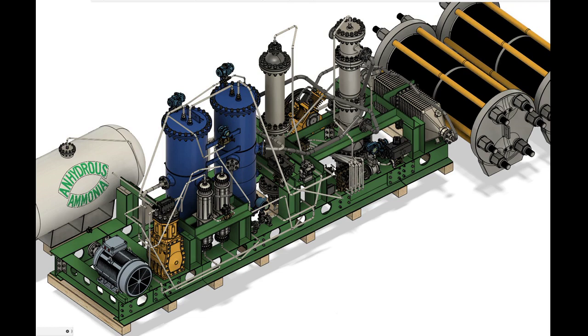In the paper, Hydrogen Attack on Metals at High Temperatures and Pressures, Corrosion and Material Protect, by J. Schutten, 1947. ASTM A387, Grade 11, UNS number K11789, is a low-carbon, 1.25 chromium, 0.5 molybdenum steel. This alloy was found to be highly resistant to hydrogen attack under the most severe conditions encountered in NH3 synthesis, and variants of this alloy have been used to date.